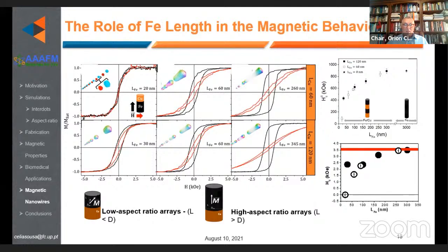We also tuned the thickness of the iron nanowires from 20 nanometers, like a disc, up to 300 nanometers in length in the case where we have high aspect ratio nanowires. And as we can see here, we can go from a low aspect ratio behavior of the particles with an isotropic behavior up to the behavior of a high aspect ratio nanowire dominated by the shape anisotropy.